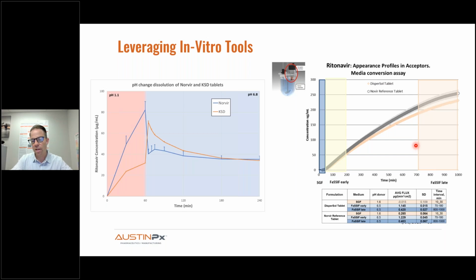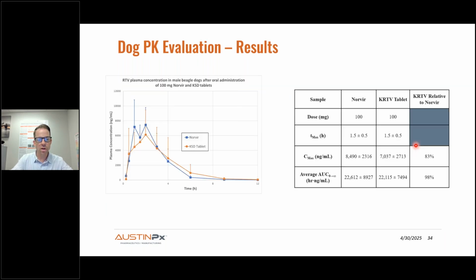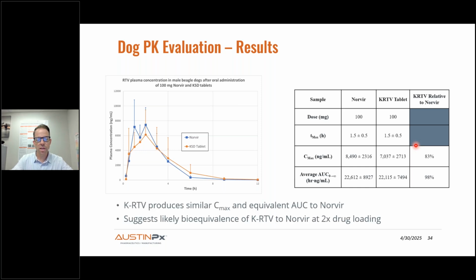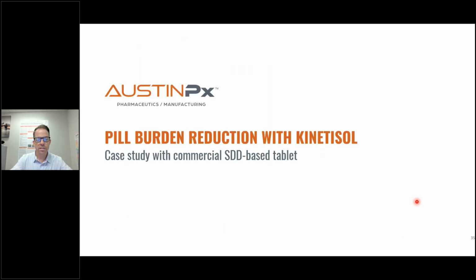And then when we look at the flux, the transmembrane flux of ritonavir from both systems is fairly similar. And then when we went into dog PK, what we saw at 2x the drug load in our KinetiSol tablet, we are, based on AUC, essentially equivalent to Norvir. So by judicious selection, right polymer, optimizing drug load, we were able to get bioequivalence at twice the drug load.